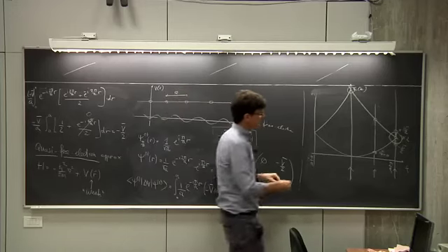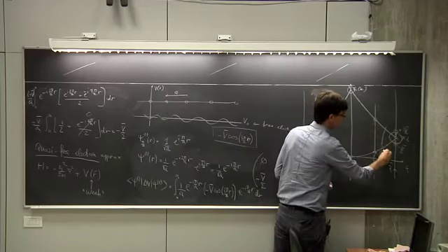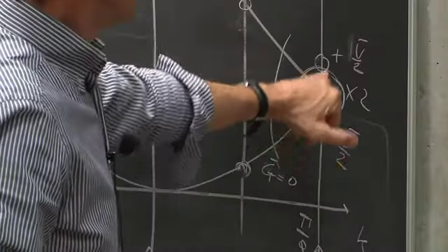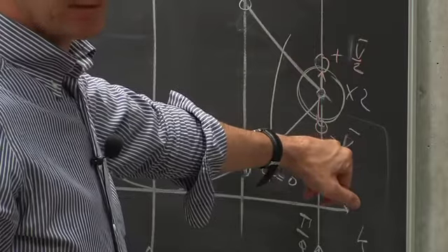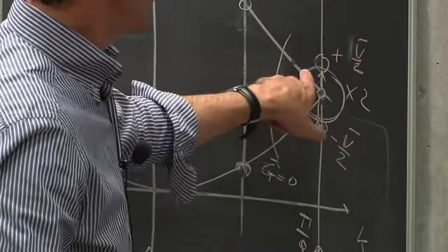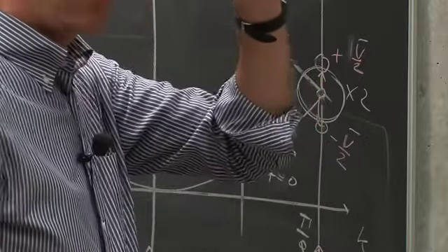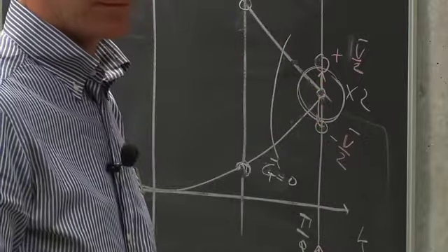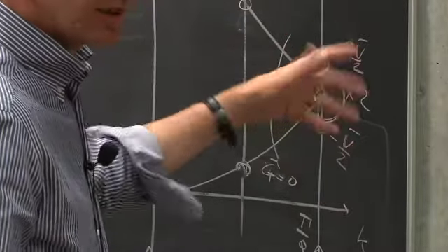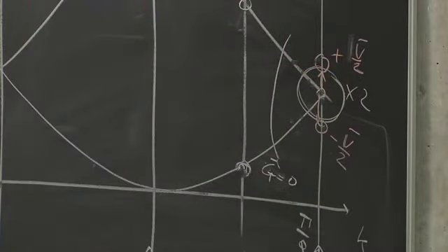So you see, as soon as we enter this region of K, we need to introduce explicitly perturbation theory for degenerate states in order to deal with these states which are progressively closer and closer to one another. As soon as this distance becomes less than V bar, we need to treat the system with degenerate theory.